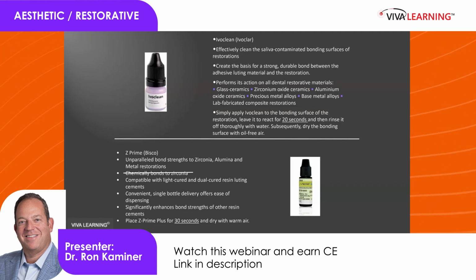Probably my go-to for years has been a Bisco product called Z-Prime. And Z-Prime gives you outstanding bond strength to zirconia, alumina, and metal restorations. It's compatible with light-cured and dual-cured resin cements. It comes conveniently in a bottle. You place a drop in your crown, let it sit for 30 seconds, air dry it, and you'll see the intaglio surface looking very, very shiny.